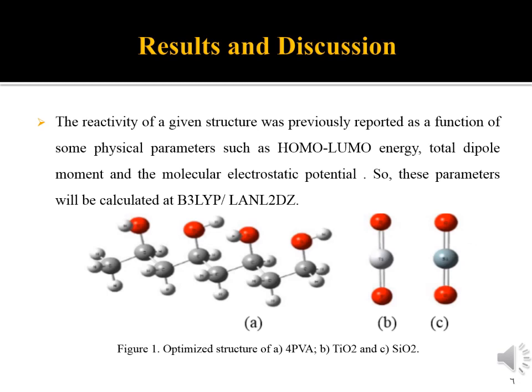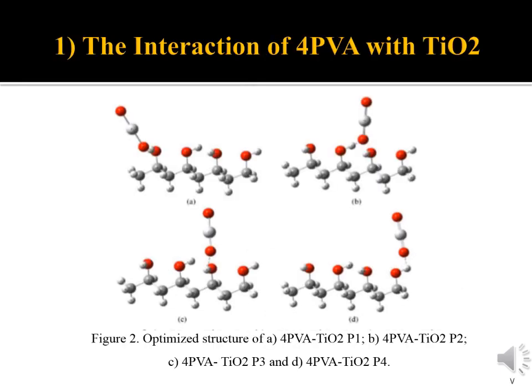Results and discussion. The reactivity of a given structure was reported as a function of some physical parameters such as HOMO-LUMO energy, total dipole moment, and molecular electrostatic potential, as we said before. So these parameters were calculated at B3LYP with basis set LANL2DZ. Figure 1 presents optimized structures of Figure A, 4 units of polyvinyl alcohol, Figure B, titanium dioxide, and Figure C, silicon dioxide. First, the interaction of 4 polyvinyl alcohol with titanium dioxide.